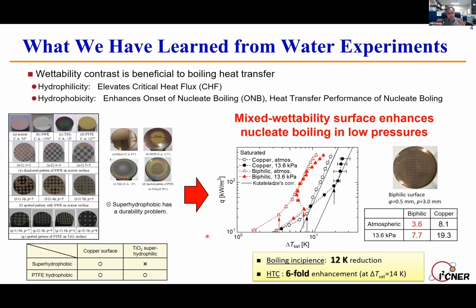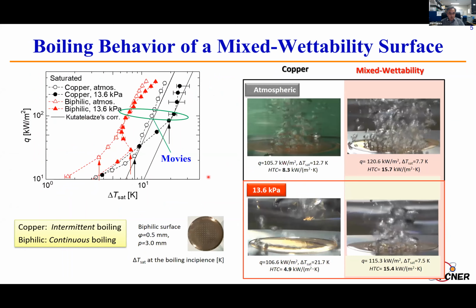So therefore, we have prepared a wettability mixed surface like this. Hydrophilicity elevates CHF, and hydrophobicity enhances the ONB and gives high heat transfer performance of nucleate boiling. And it works even at subatmospheric pressure. This graph shows the result of nucleate boiling at atmospheric pressure and low pressure. And also we can improve the onset of nucleate boiling. Okay. So the next slide shows the movie.